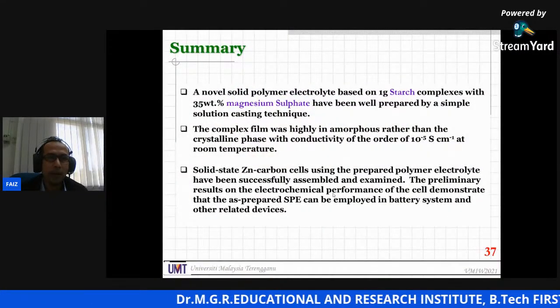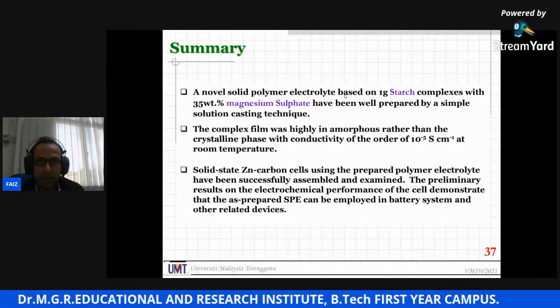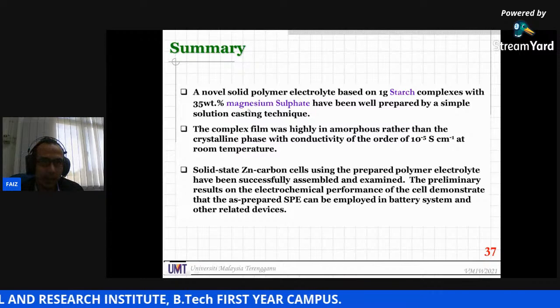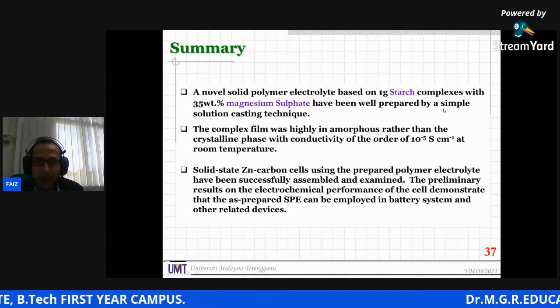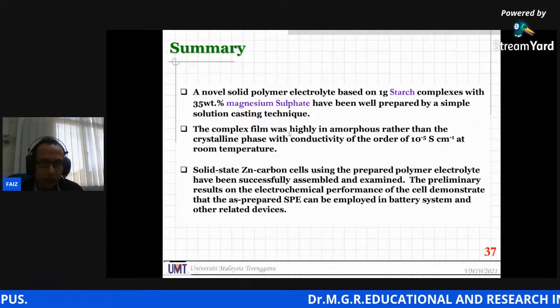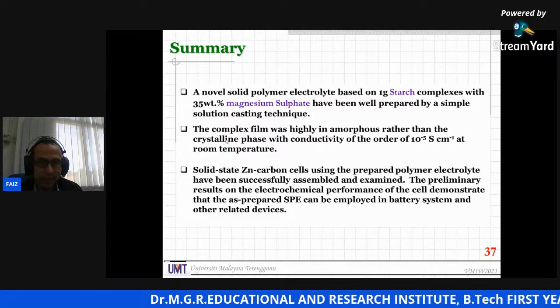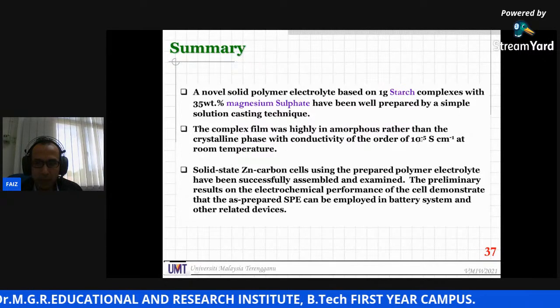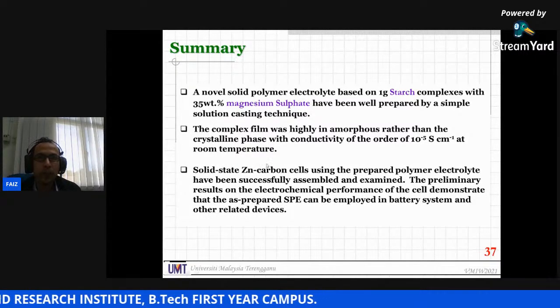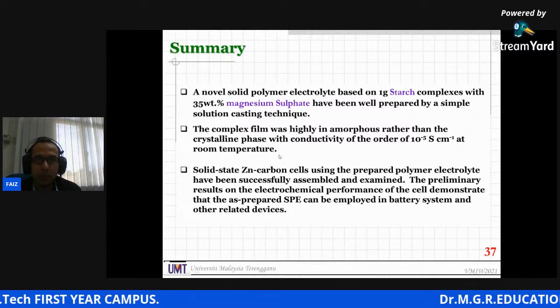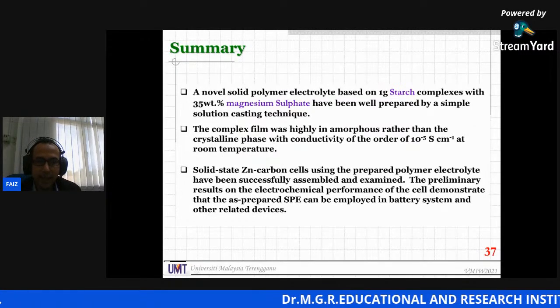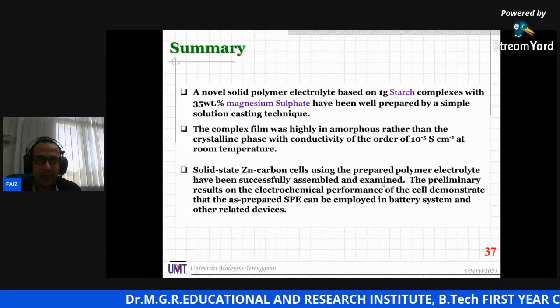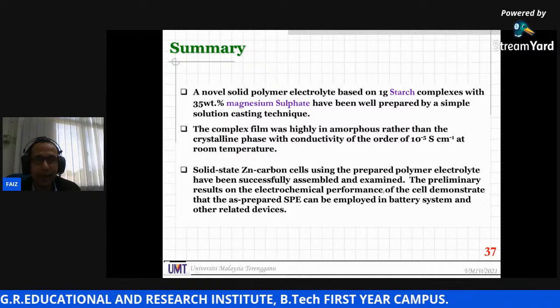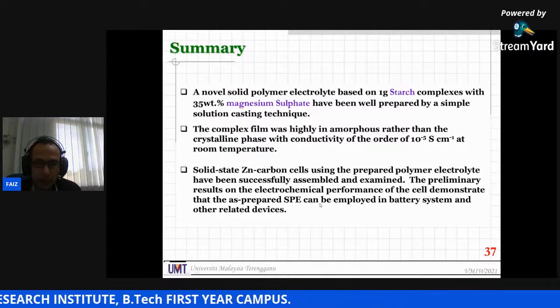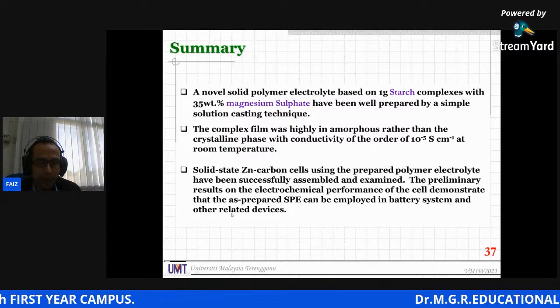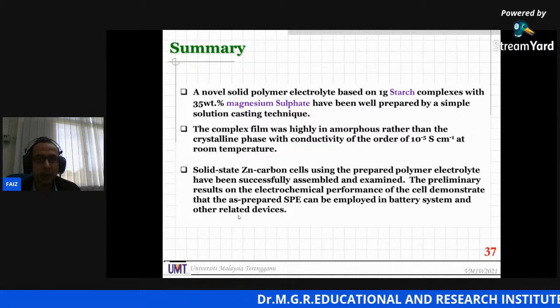Okay, as the summary for this part, a novel solid polymer electrolyte based on starch complexed with magnesium sulphate has been well prepared by a simple solution casting technique. The complex film was highly amorphous rather than crystalline, with a conductivity on the order of 10 to the power of negative 5 S per centimeter at room temperature. And a solid state zinc carbon cell using the prepared polymer electrolyte has been successfully assembled and examined. The preliminary result on the electrochemical performance of the cell demonstrates that the as-prepared solid polymer electrolyte can be employed in battery systems and maybe in other related devices.